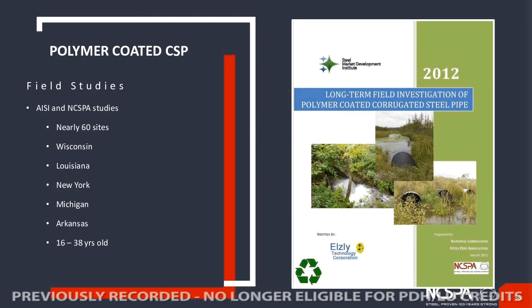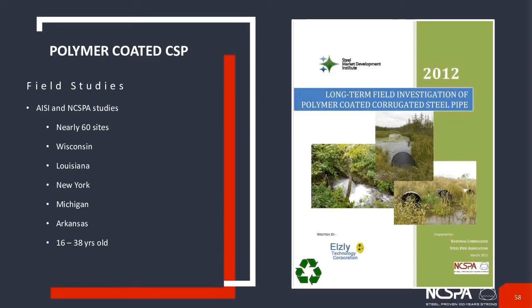But you can see from some of the pictures there, these are in some pretty brackish waters, especially in Louisiana. The sites in Wisconsin are underwater mostly, in proximity to cranberry bogs and that sort of thing. So not the most benign of sites. And then the particular sites in New York are along up to Olympic Park, and it's a pretty mountainous terrain there, and pretty high flows, pretty aggressive and abrasive areas.